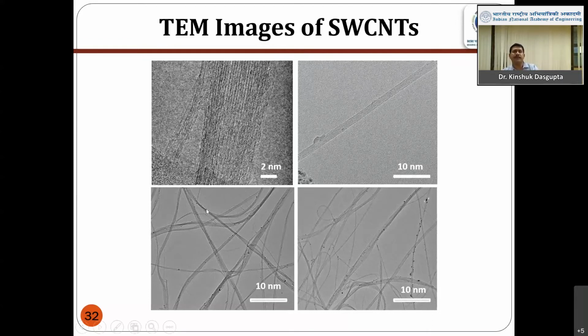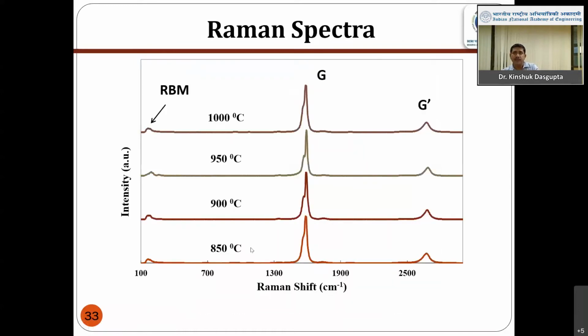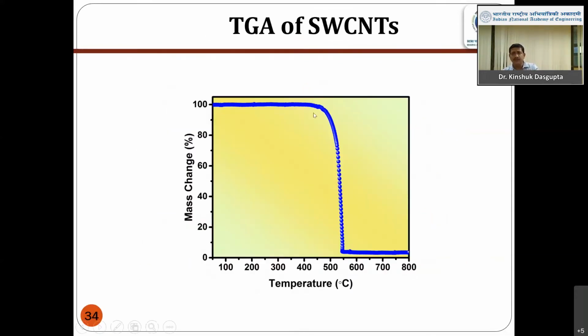But if you are able to separate them by means of high energy sonication, then you can see the single nanotubes, that is, single wall nanotubes. And if we see under Raman spectra, as I told, the D peak is gone. Rather you get an RBM, the radial breathing mode peak, and from this peak you can even calculate the diameter of the carbon nanotube. In TG thermogravimetry, here also you get a sharp fall, because there is only one wall. As soon as it starts oxidizing, there is a sharp fall in the mass in the oxygen atmosphere.